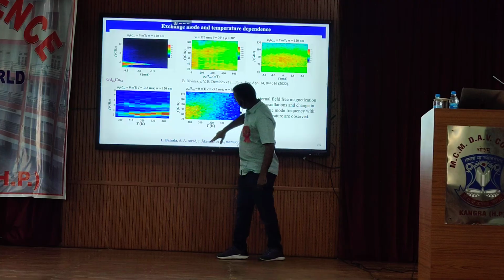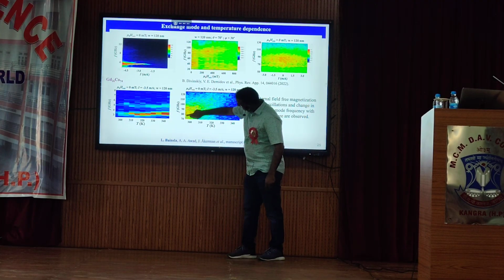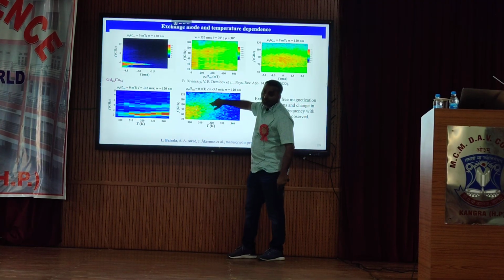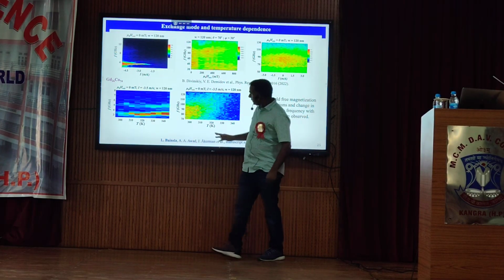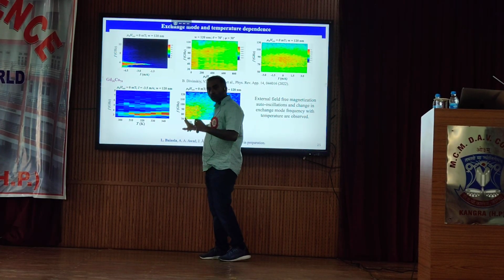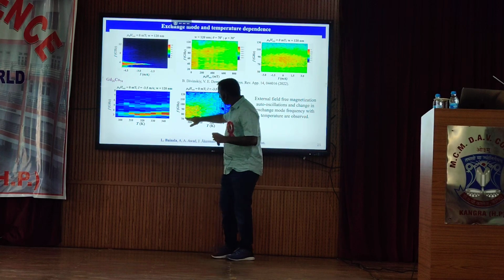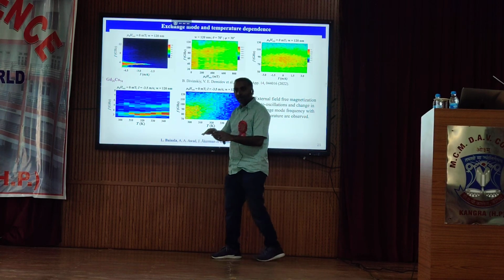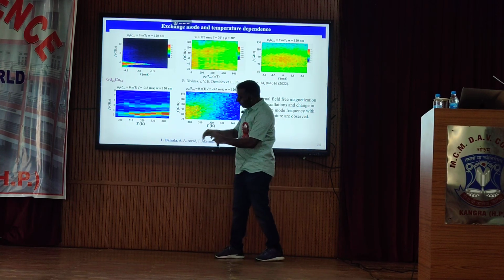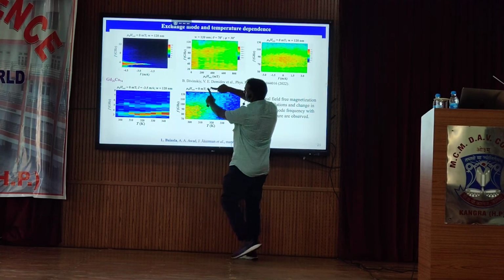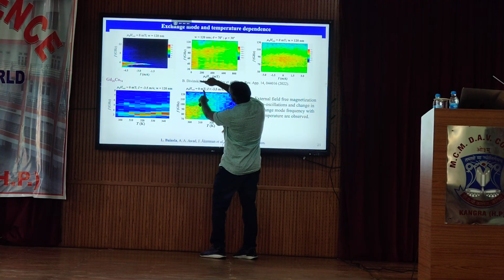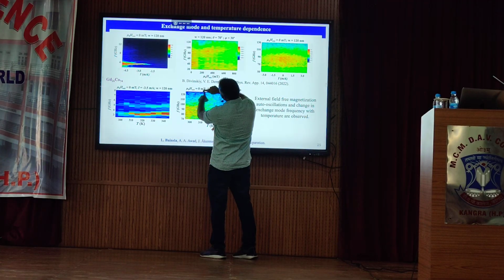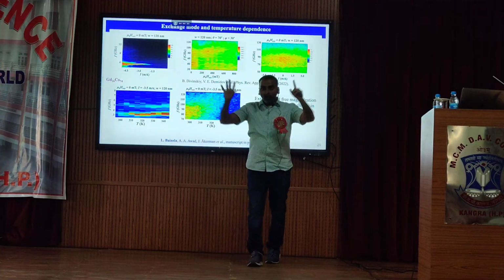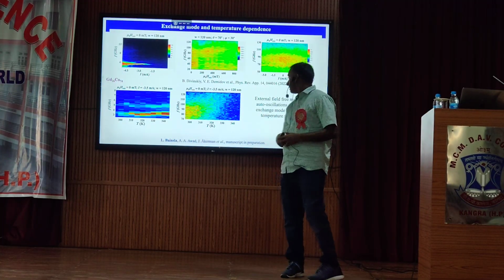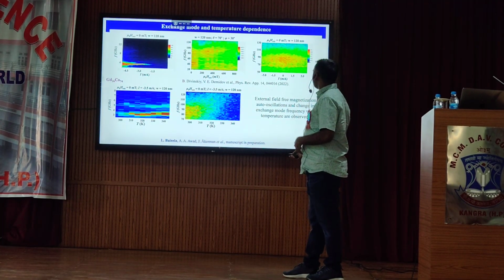So what we see here, when we change the temperature, is that the line width of the exchange mode is increasing. So what it says is that this temperature was close to the angular momentum compensation point, but when we increase the temperature, we are moving slightly away from the compensation point. As I said before, near the compensation point we have the lowest frequency for the exchange mode, and then this frequency increases when we move away from the compensation point. So that we confirm in our devices.